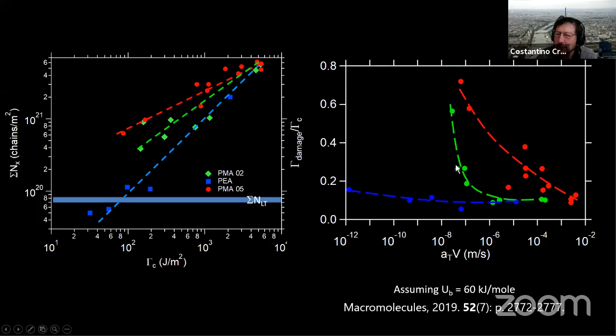But it does increase with different rates. So clearly, the details of the network structure matter in terms of the importance that bond scission has for the overall fracture energy, which is not something completely obvious to us. But you can still see the clear trend. So there is a transition between a regime close to the glass transition where viscoelastic dissipation dominates, to a regime far from the glass transition where bond scission starts to dominate. And the transition is indeed continuous. This is because the energy due to bond scission increases less rapidly than the viscoelastic friction.